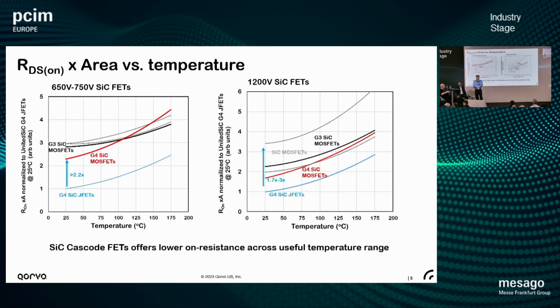Now, the JFETs are fairly ideal now, and so the temperature coefficient you see for them is higher than you're used to seeing for silicon carbide MOSFETs because it really represents the intrinsic physics of how the resistance of the voltage blocking layer in silicon carbide changes with temperature. And as MOSFETs evolve and other technologies evolve, pretty much all of us end up on the same kind of curve. So you can see from these curves that the generation 4 type silicon carbide MOSFETs have a somewhat steeper temperature dependence in RDS on, kind of like ours.